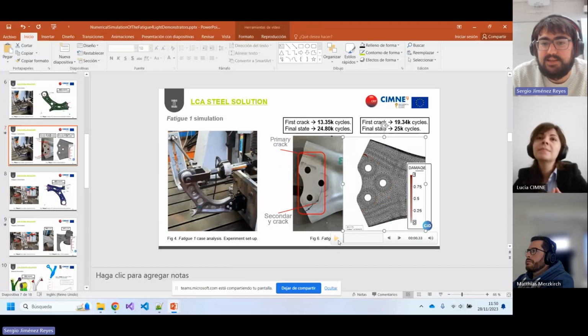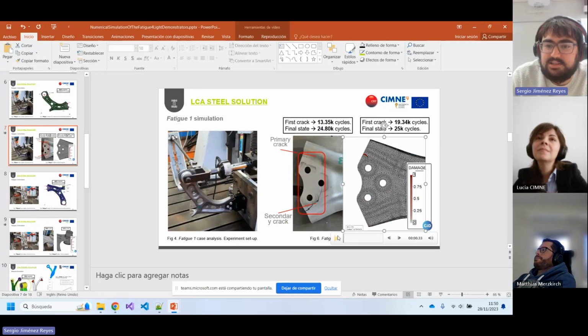And that's the point. But compared with commercial techniques, what they usually do is just run up to this point, because the usual commercial approach is just based on stress distribution. So basically what they are doing there is guessing the amount of cycles that it takes for each region, each of the points in the model, to then degrade. But if you really want to experience the degradation process in the demonstrator, it takes time.